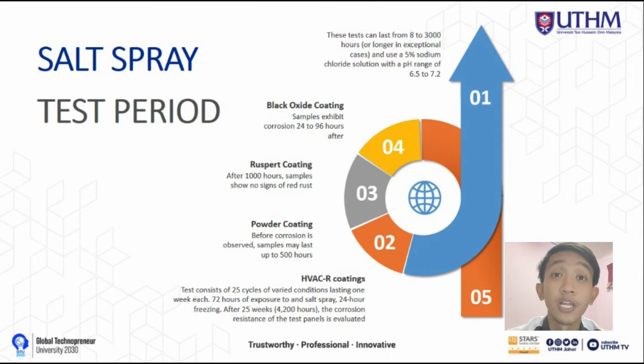Okay, now for the last part, we are going to the salt spray test period. So basically this test can last from 8 to 3,000 hours or longer in exceptional cases, and uses a 5% sodium chloride solution with a pH range from 6.5 to 7.2. So basically, when we are using the material with black oxide coating, the sample exhibits corrosion 24 hours to 96 hours after.